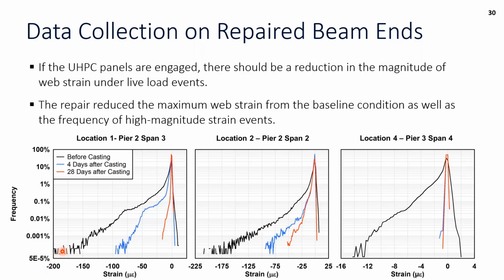And you can see before casting, we were getting around 200 microstrain. And then once we reached our 28 days after, we're now below 25. And this is really going to vary depending on what that initial strain is, how much deterioration we have first and foremost. But we did see a reduction in all of those high magnitude strain events.